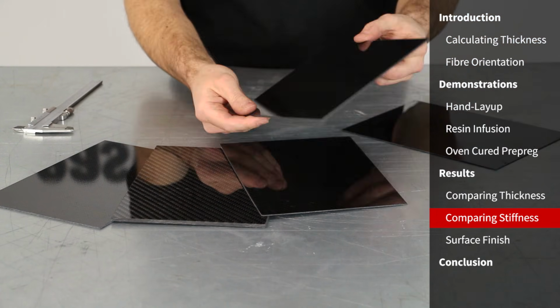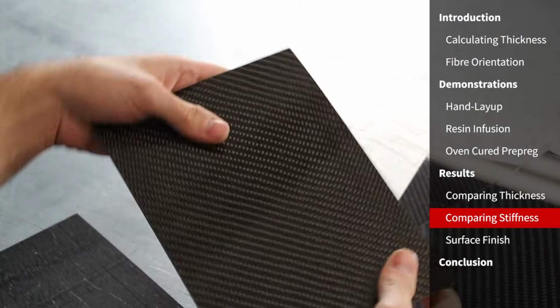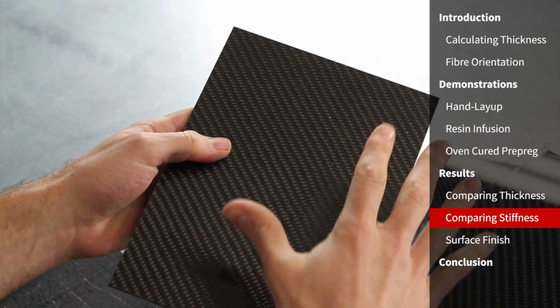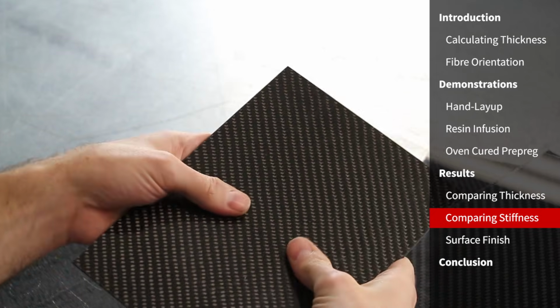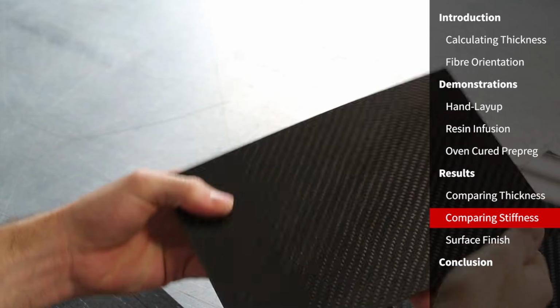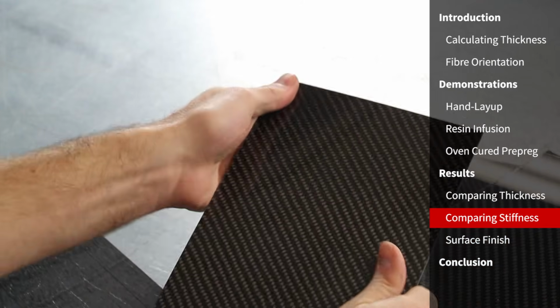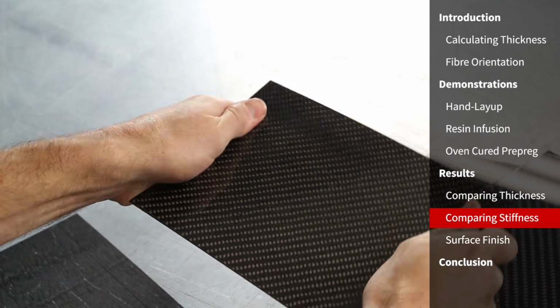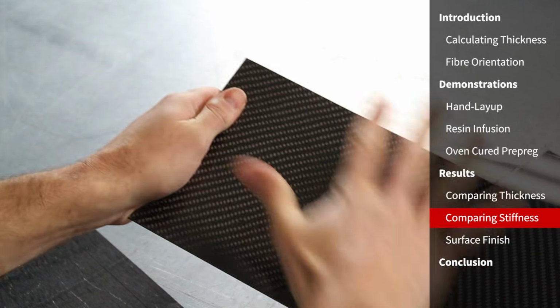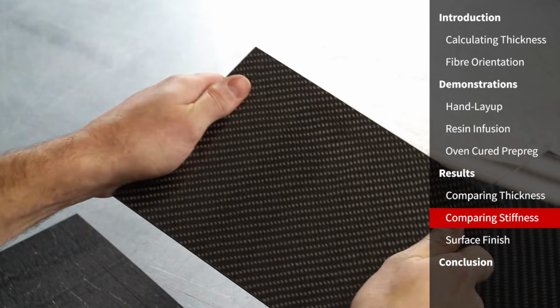In the second wet lay sheet, we tried to create pretty much the opposite of the unidirectional, which was to create a sheet where we'd got an even distribution of the strength, so across its width and its length, and then also on the 45-degree axis. So torsionally resulted in a very even balance of the strength on this sheet.